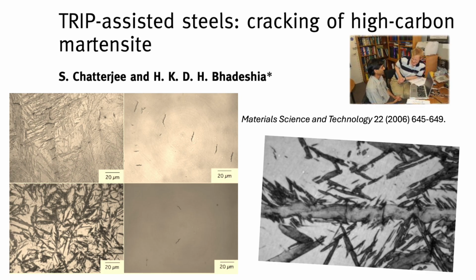Okay, so we can manage distortion to some extent, but you mentioned shattering earlier. Let's talk about cracking. Yes, cracking. That's the real killer, especially in high-strength steels. And what's fascinating, really key here, is that the cracking usually comes from 2 different types of internal stress building up at the same time. 2 types, okay. And we need to remember, we're often dealing with strong steels, the ones that get their strength from a martensitic microstructure. These are inherently less forgiving. They don't easily deform to relieve stress.